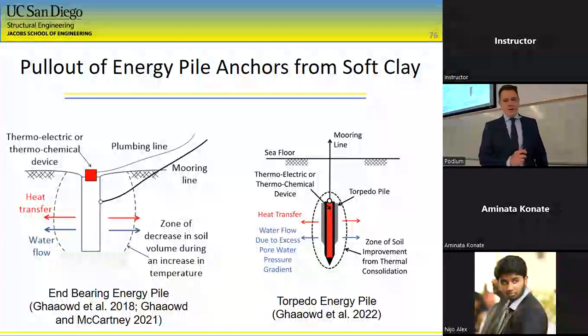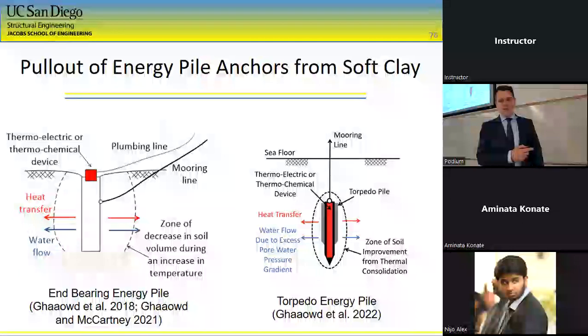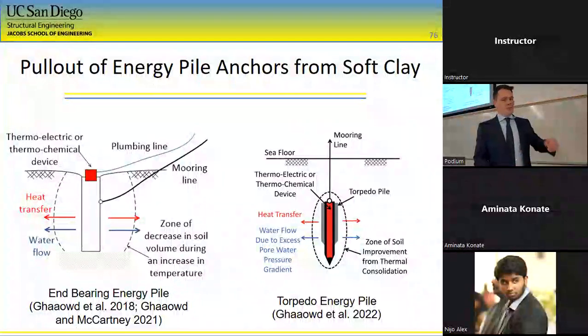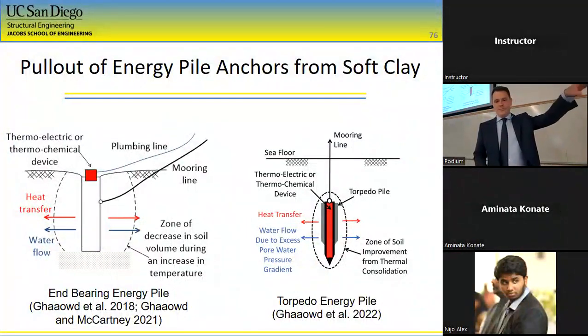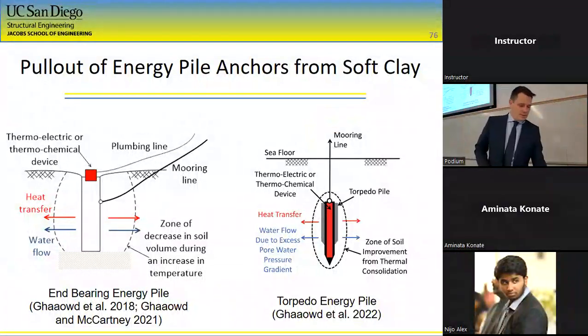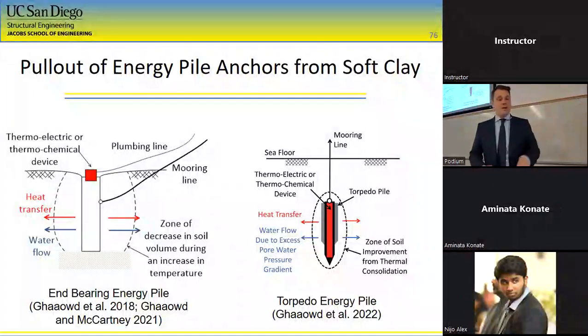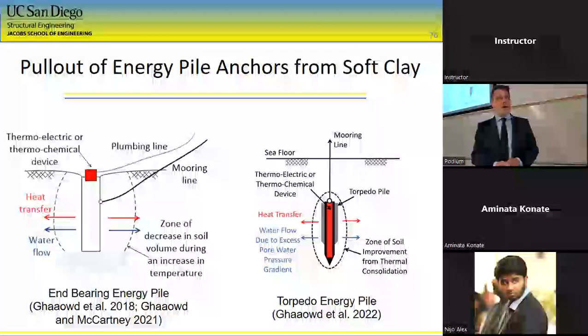This is where we wanted to test the effect of temperature on the pullout of piles in soft clay. We did one that has an end-bearing pile and these torpedo piles. So the way that you would do this, if you're in the Gulf of Mexico, a torpedo pile, you would drop this off the side of a ship. It would embed itself below the seabed surface. And then you would have an electrical cable connected to it, and you would heat the pile up.